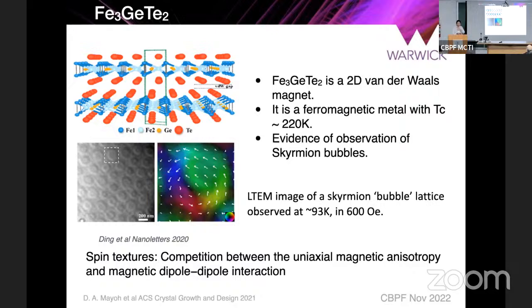So the skyrmions actually form a lattice. By analogy, you can compare these with the vortices in a type 2 superconductor, for example. So you can also use small angle neutron scattering to study this lattice of skyrmions. And in Lorentz transmission electron microscopy, you apply a magnetic field and you just change the focus, and you need to be a real expert to be able to extract this information from these materials. They are able to image these skyrmions in very thin lamellae of the materials.